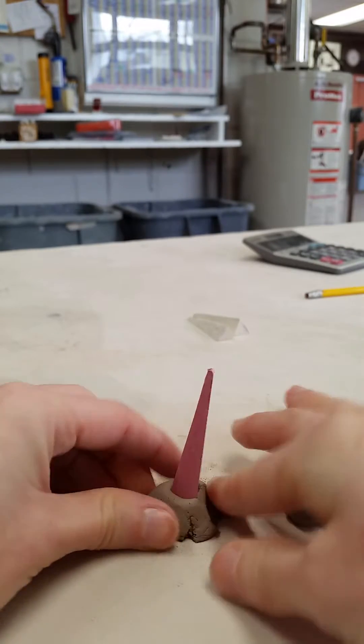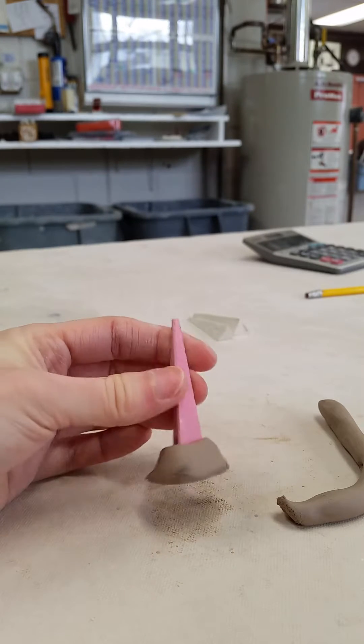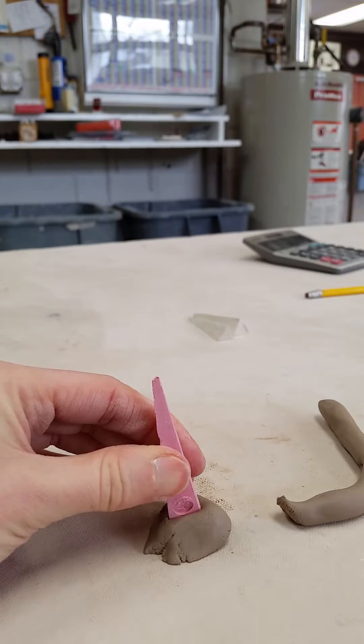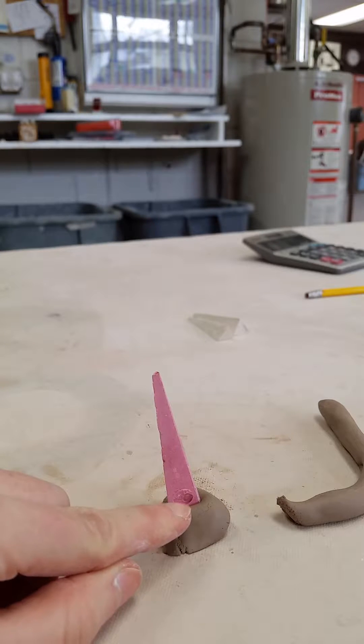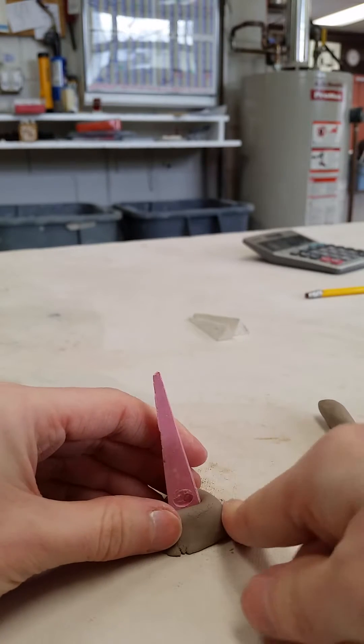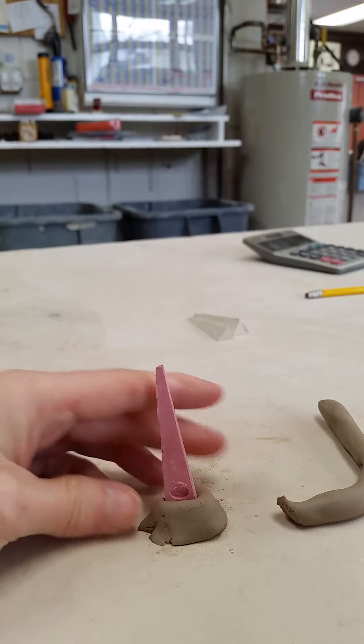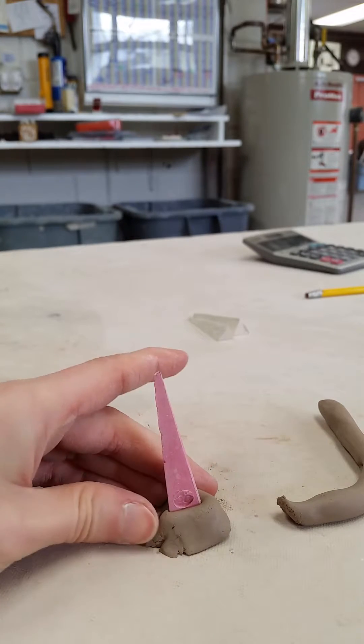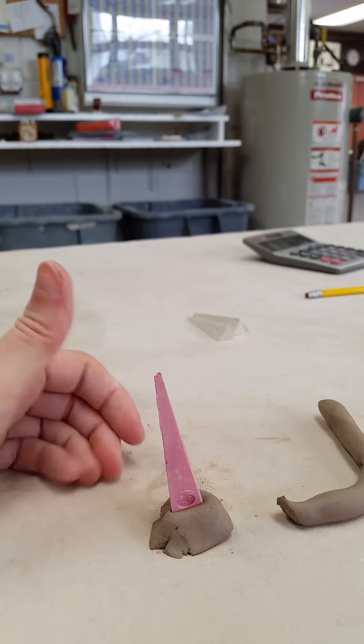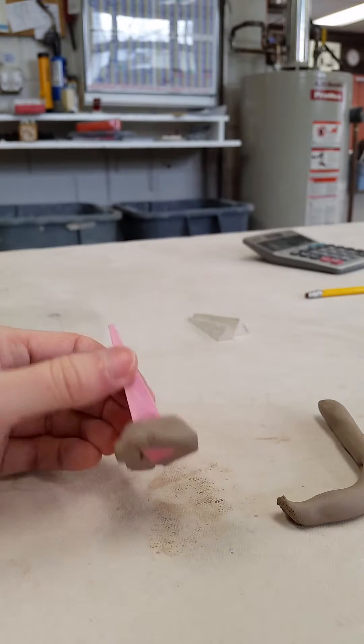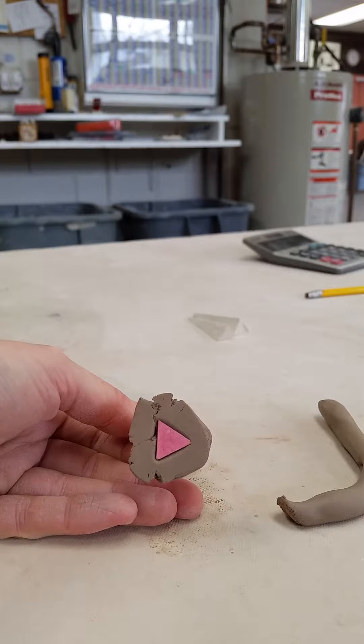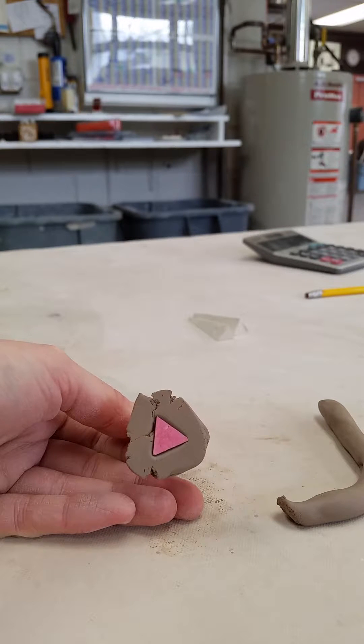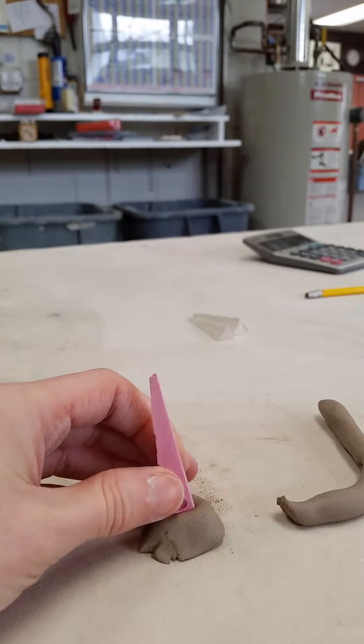We're just doing one. You can just wrap your coil around all the way. You can see that it's mounted right up to the bottom of that line, that circle there. If you wanted to go back in with a fettling knife and cut away some of this excess clay, like if you're making your cone pack at the very last minute, you can of course do that and poke it full of holes if you'd like to. You can also see that the very bottom of the cone—there's no clay stuck underneath there, so we know that is at the exact right angle.